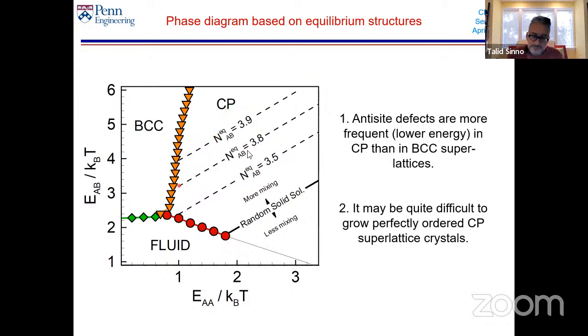These lines represent the ideal ordering, or the ordering extent. So if I come this way, or I'm up here, I'm going to have a high degree of ordering. If I come down here, I'm going to have a lower degree of ordering. And by the time I get to this line, it's still close packed, but I'm going to have a random mixture of A's and B's in the system.